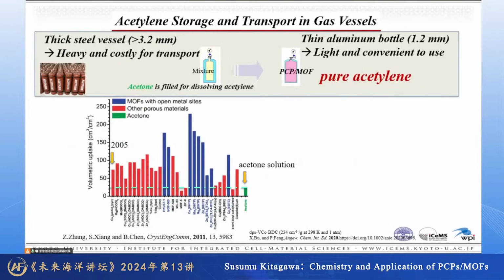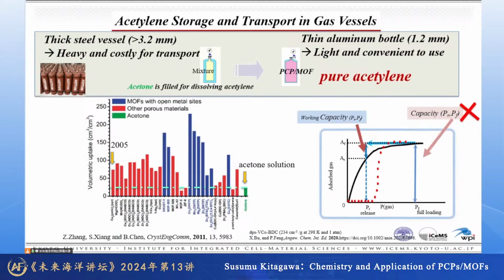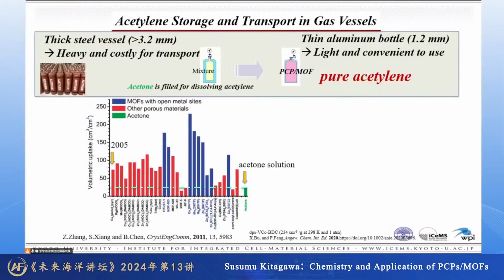After that, many people are synthesizing this kind of acetylene storage. This is our case. Increasing more looks fantastic, but there are still problems for the application. This is a type 1 isotherm. Usually you get this kind of desorption profile. This case shows this one. Okay, full loading. This shows the full loading capacity. But if we reduce the pressure to this position, only this part is usable. We call it the working capacity. Working capacity is not so good. If we have this kind of sigmoidal curve here, most of the absorbed amount can be used. So still this has a problem.